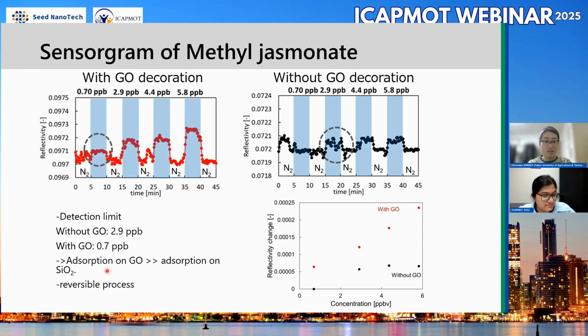So these results show the adsorption on graphene oxide is much higher than the adsorption on SiO2, as shown in this summary. And this adsorption and desorption process is a reversible process. So we can use this sensor many times.